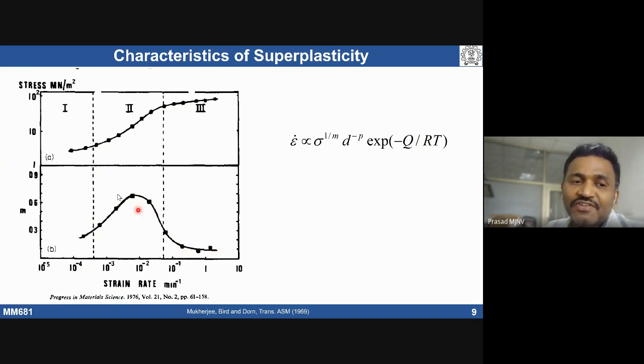Depending on strain rate sensitivity, your ductility is also going to vary in a similar fashion, because the previous slide showed m and delta L by L. So from this curve we can get the strain rate sensitivity, and then we get a bell-shaped curve between strain rate sensitivity and strain rate, or ductility versus strain rate. This is the characteristic behavior of superplastic materials. There are three regions: region 1, region 2, and region 3. The superplasticity window is region 2.